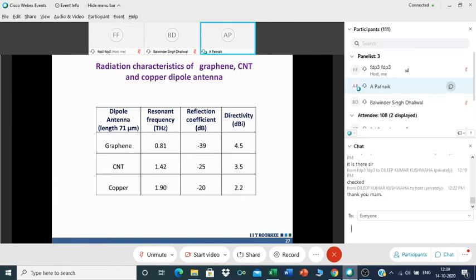So then we compared the radiation characteristics of all the three antennas made up of graphene, CNT and copper dipole. You can find that, as I told you, graphene is resonating at a very low frequency compared to the other ones. Not only that, the reflection coefficient is much better than the other two, and you are getting a directivity which is much higher than the directivity of the other two antennas. If the physical size remains the same, you are getting better performance in case of graphene antennas, right?